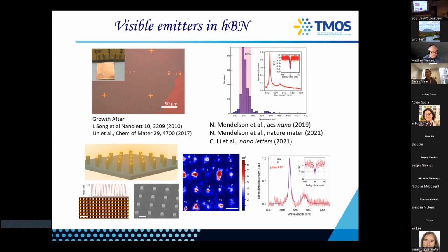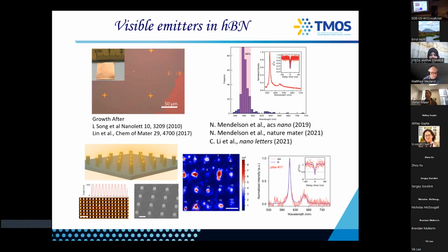Now, before we get there, we need to engineer the emitters. I'm just going to reference most of the work here; some of it is ours, some of it is not. We can now grow HBN on what people in the semiconductor industry call wafer scale. We say copper scale, because it's just on copper. You buy copper, heat it up to about 1,000 degrees, and grow HBN. The material quality here is very low. It's all polycrystalline with very small grains, but for single emitters, it's actually quite good.